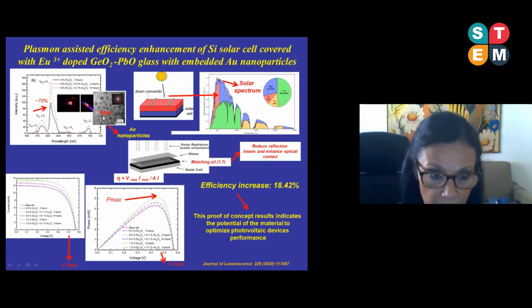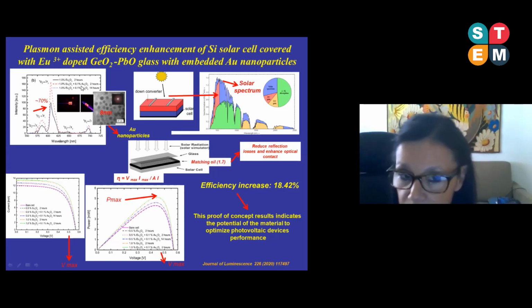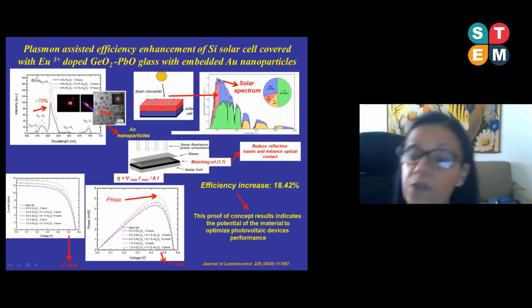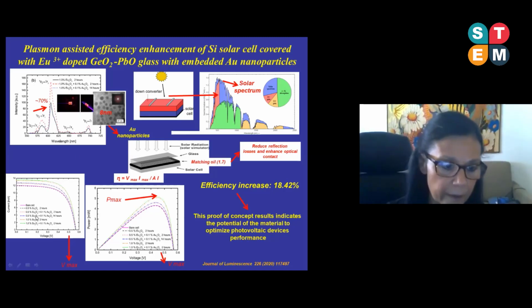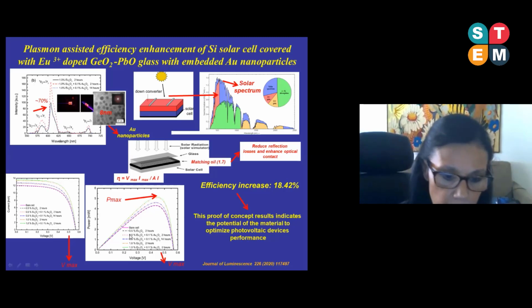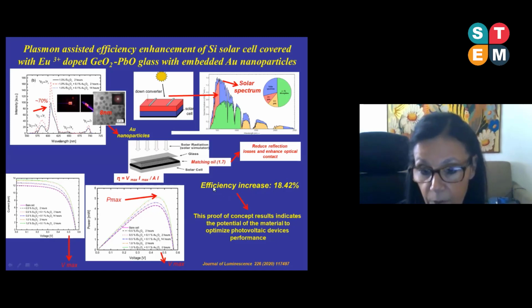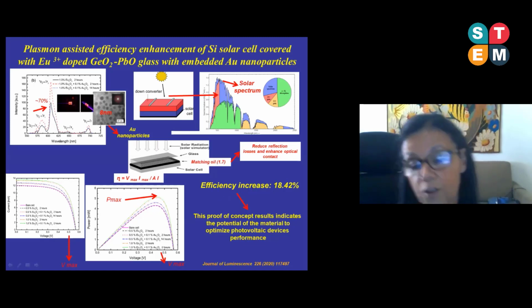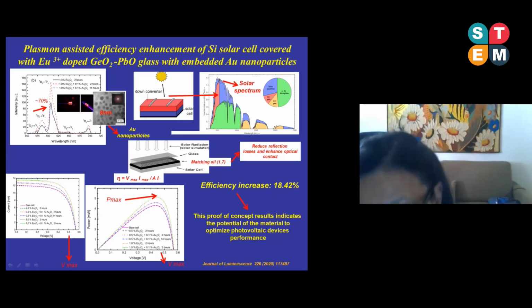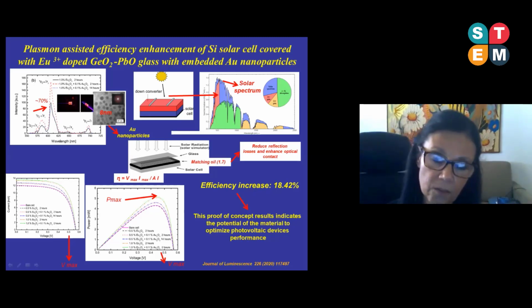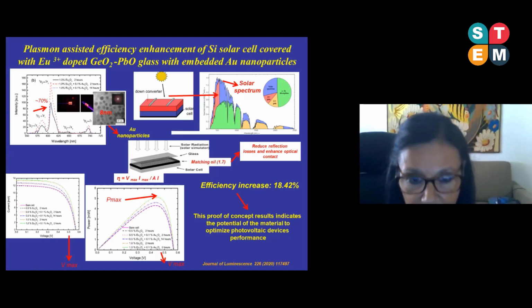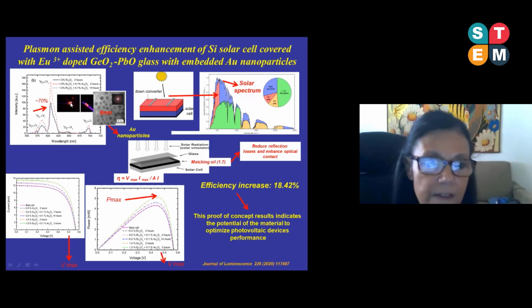nanoparticles with size around 8 nanometers, we decided to use this material to cover a commercial silicon solar cell, but varying a little bit the concentration of europium, the concentration of gold. And then we obtained very interesting results, the best result that shows us an efficiency increase of about 18% when the silicon solar cell was covered by the material that exhibited the largest luminescence, this one that I showed before, due to this strong red light that was emitted.